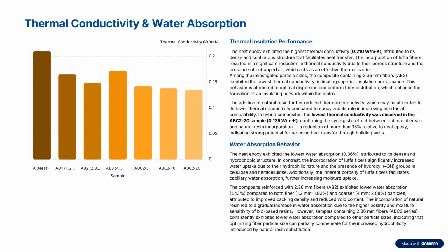The water absorption also shows its lowest value for the neat epoxy at 0.36%, attributed to its dense structure. In contrast, the incorporation of Luffa fiber significantly increased the water uptake due to its hydrophilic nature and the presence of OH groups in cellulose and hemicellulose.